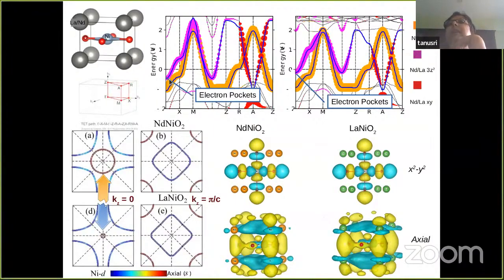But in addition, there is another band that is crossing the Fermi level and giving rise to an electron pocket, and that primarily comes from neodymium or lanthanum 3z² and xy, and that gives rise to two pockets, one at the gamma point and another pocket at the A point. And if you really look at the Fermi surface, you find that the Fermi surface looks more like that of the cuprate, but with a big exception. Around the gamma point, you do have a pocket, which is this electron pocket. And the size of this electron pocket is quite different between the neodymium and the lanthanum compound.